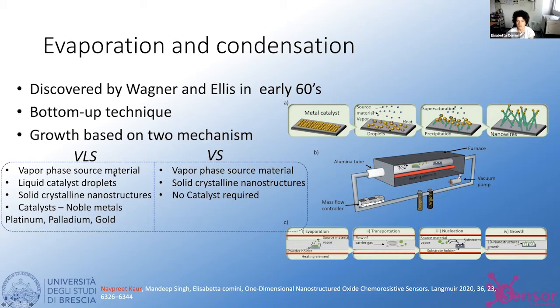And you can use two different ways. So you can use the VLS growth mechanism, which is vapor liquid solid, where you have a metal catalyst that during growth becomes liquid, and is a preferential condensation site for the vapor that you need to create in the furnace. On the other hand, you can also use the vapor solid growth, where no metal catalyst is required. The system is this one, and you have a tubular furnace where you put your metal oxide powder in the higher temperature region, and in the lower temperature region you put your substrate.